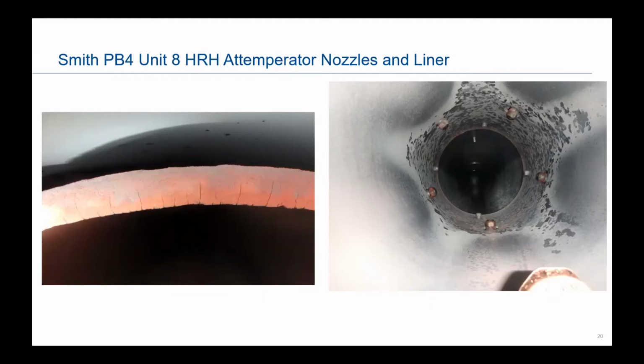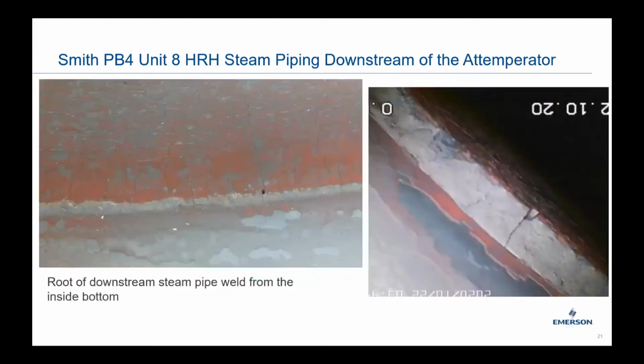Additionally, at the same site, the first weld downstream of the liner, that you'll see in the next photo, was developing cracks in the weld itself. And that was where you saw that view in that second photo on the previous slide, where we actually had to cut out a section of reheat steam piping to replace that weld because the crack was actually extending into the base metal.